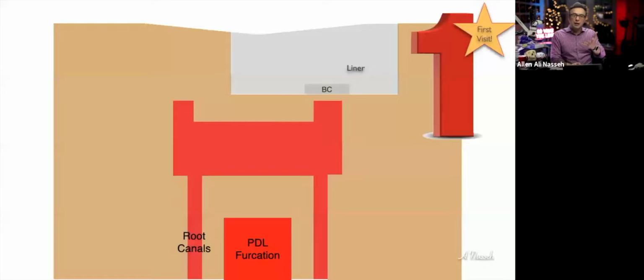So afterwards, though, this is a technique that I described called the non-surgical lid technique, in which you are using the putty for the most biocompatibility, but then quickly going on and placing the liner on top of it for restorability. So you can fill all the way up to the top in case you're doing quadrant caries control. Instead of using IRM and things like that, you place the bioceramic against the pulp after controlling the bleeding. Then you fill up all the way to the top, and this material will self-etch and self-bond, and you will be able to wait 8 weeks to figure out what's going to happen.